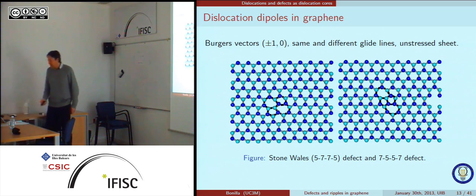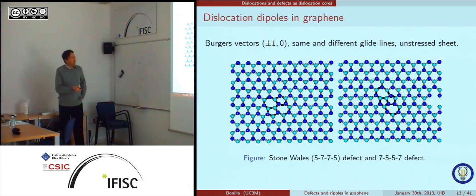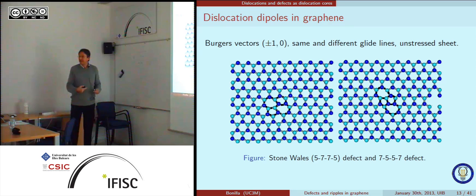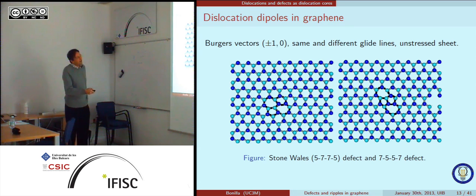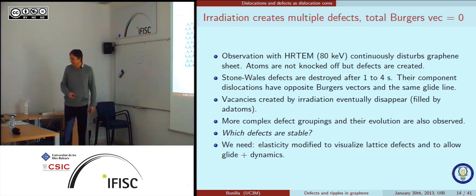undisturbed. This is also what happened in the case of the graphene lattice. So this is the 5775 defect, so two heptagons sharing one side, and two pentagons. This one is equivalent to the dipole with the two dislocations that have opposite Burgers vector but share the same glide line. So you apply this elasticity model, and this thing annihilates, and this is what happened in the experiment. Whereas if you just shift the glide lines so they are parallel but not the same, then you get a stable defect, which is in this case two pentagons sharing one side and the two heptagons above. Okay, so